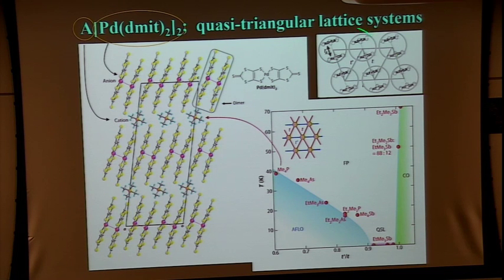And this is the in-plane structure of the molecule. This palladium DMIT2 molecule forms a strong dimer, like the materials I talked about yesterday. This strong dimer forms a two-dimensional network, and the transfer integrals roughly characterize it. Two kinds of transfer integrals are there: T prime and T. So it is an anisotropic triangular lattice. And the very good point of these materials is that they have very finely tuned parameters for the anisotropies.